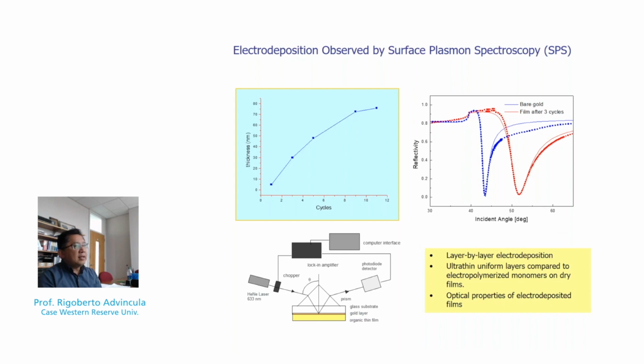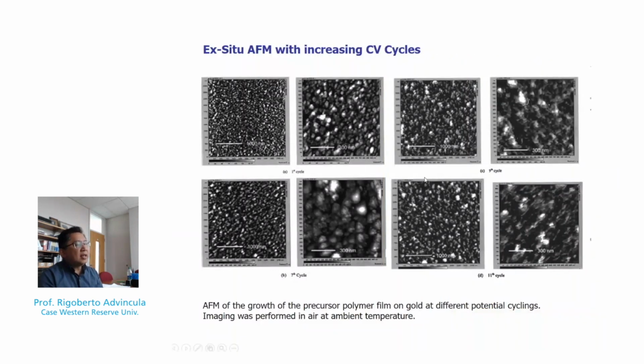polythiophene. Now, ex-situ wise, we then investigated by AFM the morphology, both on the topological and phase imaging, the domain behavior as we increase the number of layers deposited. So AFM here was used ex-situ, meaning after we have deposited the film. So in this case, we can see that the domain sizes increase as we have more films deposited. We actually have some AFM imaging that distinguish a reduced versus an oxidized state. So this is a very good combination of the two techniques.